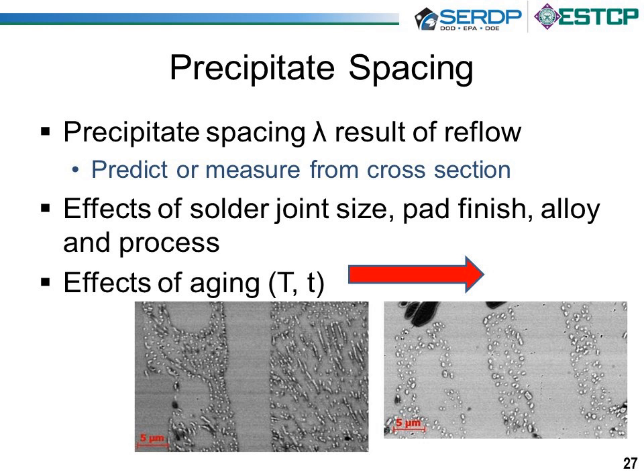It has to do with the difficulty of solidification. It's not something you normally notice if you're not into it, but in fact, the solder does not solidify when you hit the melting point when you're cooling down. And so you end up cooling it significantly below that before it solidifies. But anyway, that solidification determines the distributions of the precipitates initially, okay?